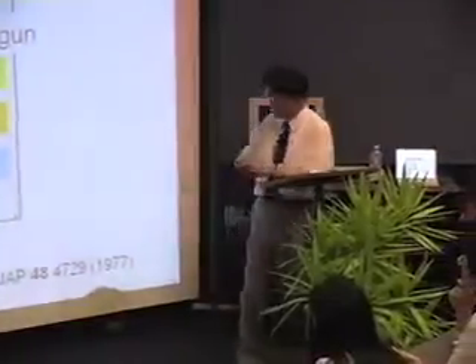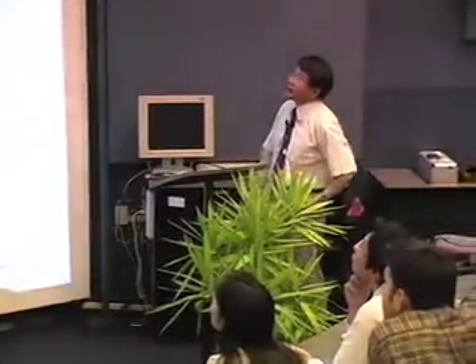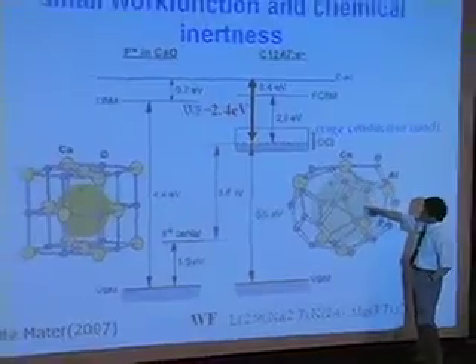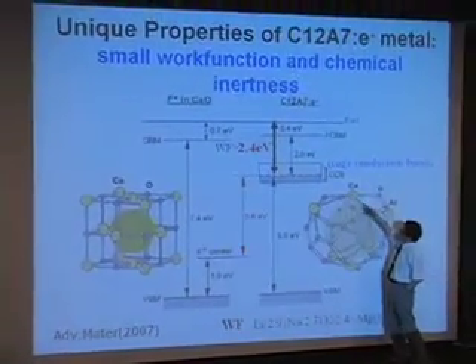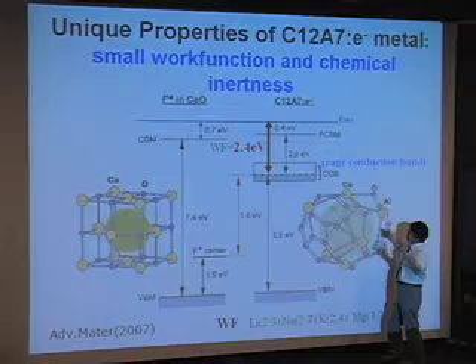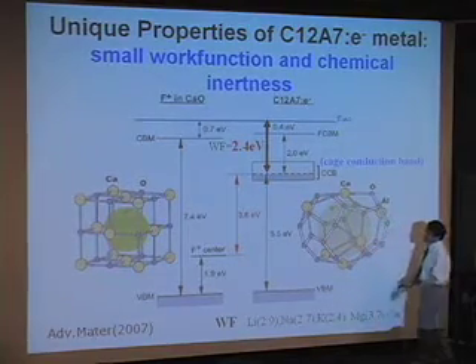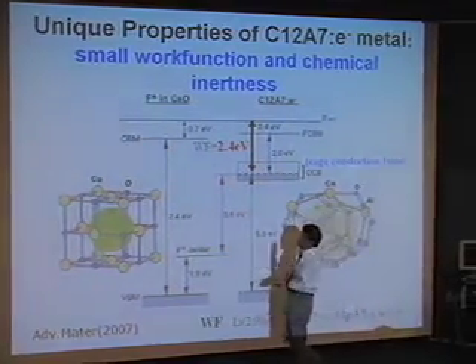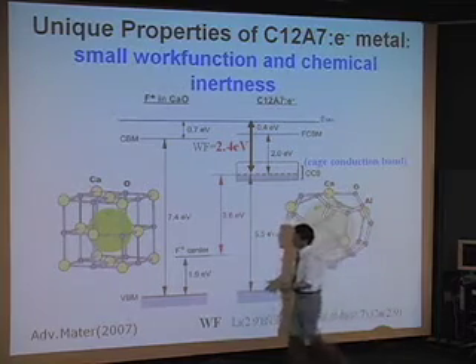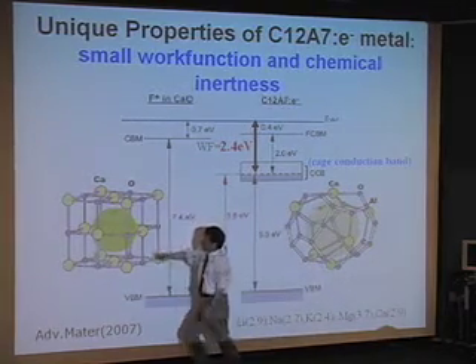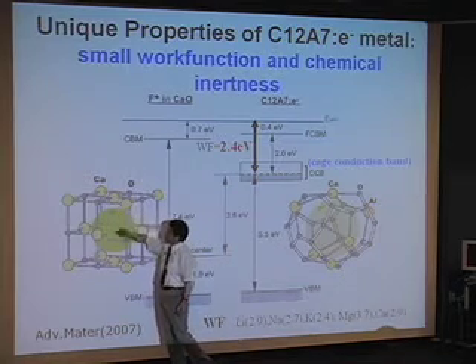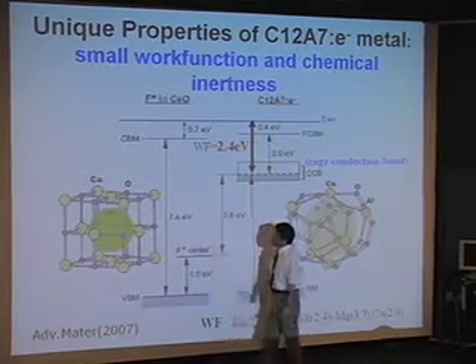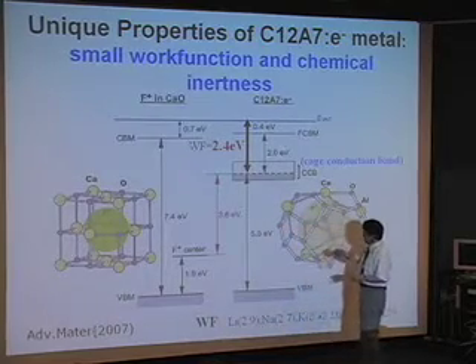What causes such a thing? This is the band structure of C12A7. This is a cage structure built from an electron, and the electron is octahedrally coordinated by 6 calcium ions. This situation is almost the same as an electron trapped at an oxygen vacancy in a CaO crystal — also coordinated by 6 calcium ions. The band structure is the same.